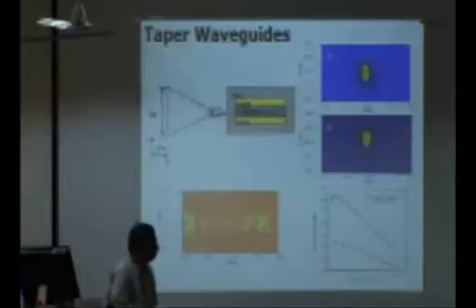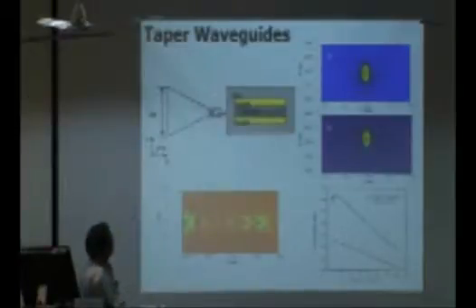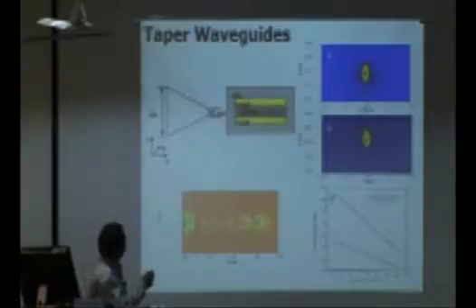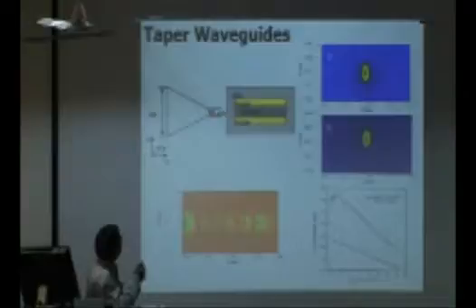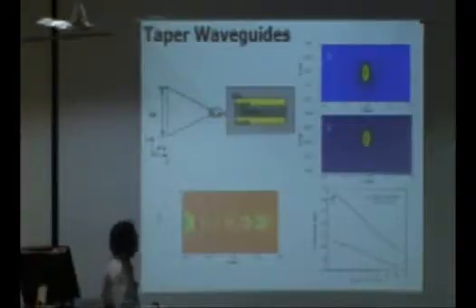Okay. We also looked at these taper waveguides. These are with a silicon core with gold on either side, and then a silicon dioxide cladding. So these are taper waveguides. We studied different geometries and showed that when we have gold and exponentially decreasing tapers, we have pretty good efficiency of coupling to the near field.